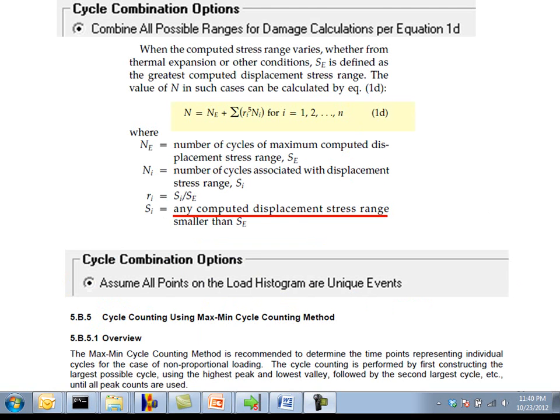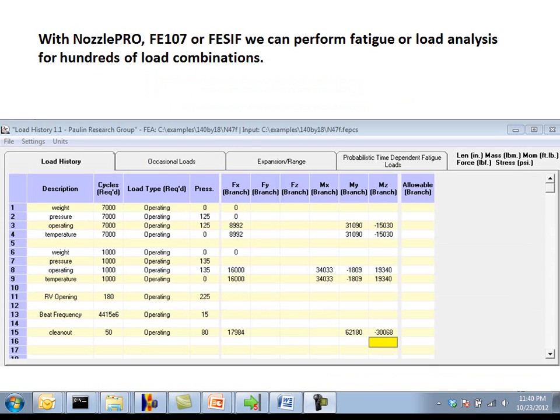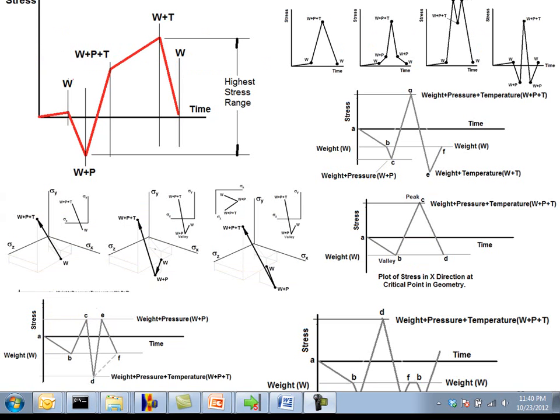We saw that the B31 equation 1D cycle combination method can be overly conservative when there are a large number of components. We also saw that the min-max cycle counting method used in Section 8, while more complicated to implement, is more realistic. We saw that Nozzle Pro and FE107 make the cycle combination calculations for piping and pressure vessels automatically. We also saw cases where WRC 107, 537, and 297 may not provide adequate results. And we saw cases where the B31 Appendix D SIFs are non-conservative, and other cases where they're overly conservative.